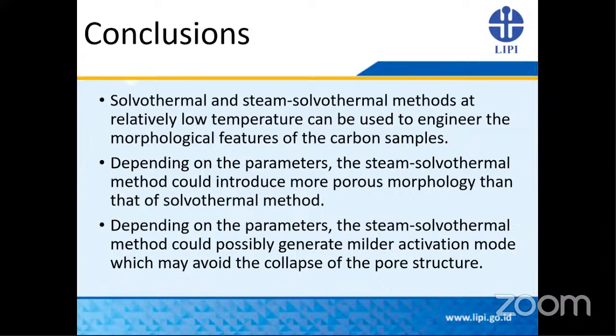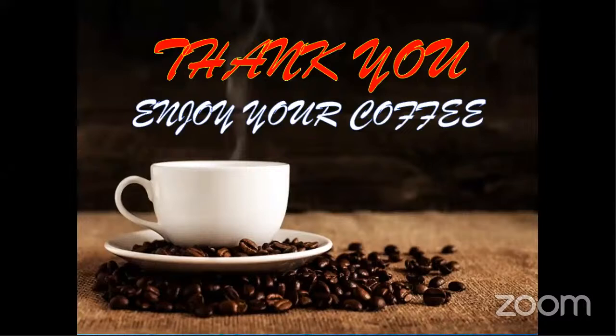So we can conclude in this research that the solvothermal and steam solvothermal methods can be used to engineer the morphological features of carbon samples at relatively low temperature, only 200 degrees C. And depending on the parameters, we could introduce a more porous morphology than that of the solvothermal method. Also, depending on the parameters, we could possibly generate a milder activation mode, which we hope can avoid the collapse of the porous structure in the carbon sample. Okay, thank you for your attention and enjoy your coffee.